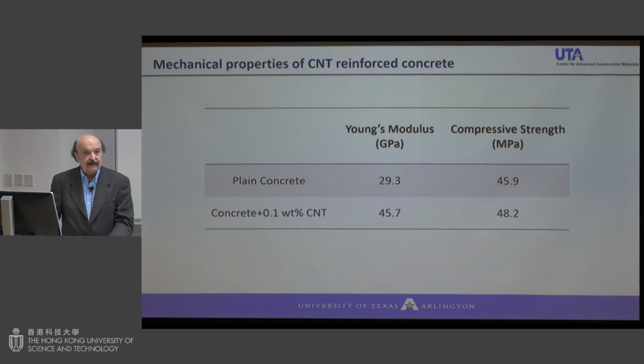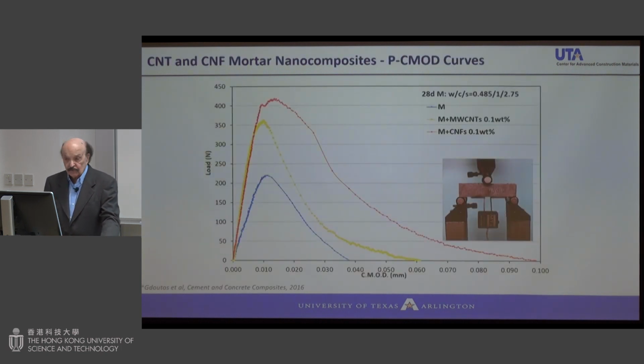I think we had done a lot of work earlier. Zhongxin had done this for super tall buildings, where you need to have a high modulus, and one of the ways is this carbon nanotube. We also find, for example, here again 0.1%, a fracture test. So plain mortar and 0.1% carbon nanofibers: you more or less double the flexural strength. So this is why we are interested in seeing how CNT can do as far as this.